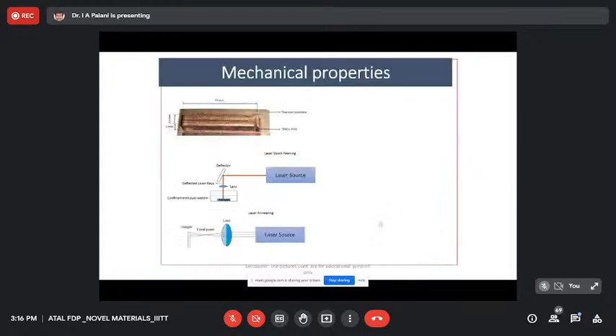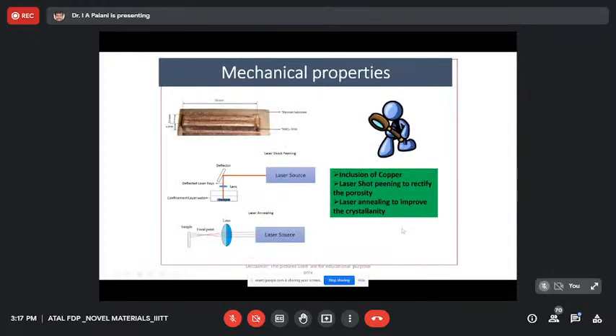Okay. So as an extension of this, since we have fabricated this structure, we could observe that mechanically there were some kinds of issues on the samples, because in this case, the material is completely heated up, and then we are trying to manipulate the structure. So when we are heating it up, obviously there is a chance of losing a certain amount of properties in the system. So in order to improve or enhance its properties, we may need to go for some kind of post-processing. So one post-processing we went for is some kind of annealing, and another is laser peening. The main important aspect of laser shock peening is to rectify the porosity, and the laser annealing is to improve the crystallinity. So basically, the idea is to go for a uniform crystallization with respect to the laser.